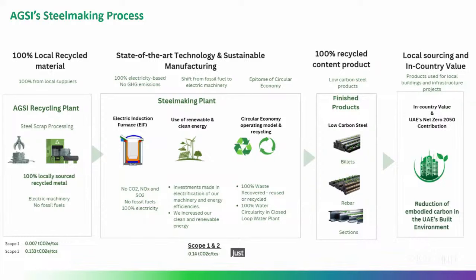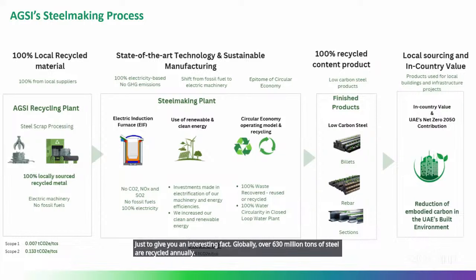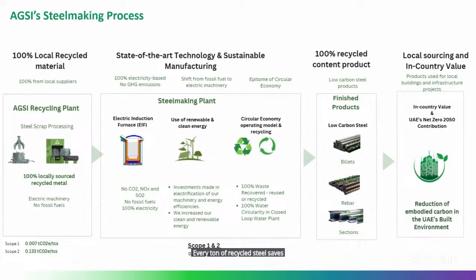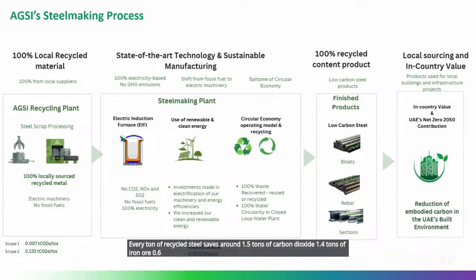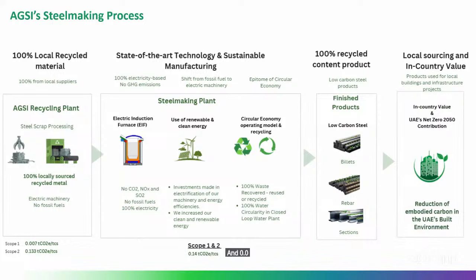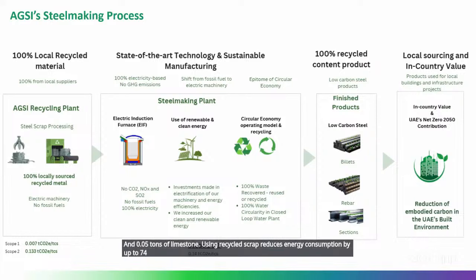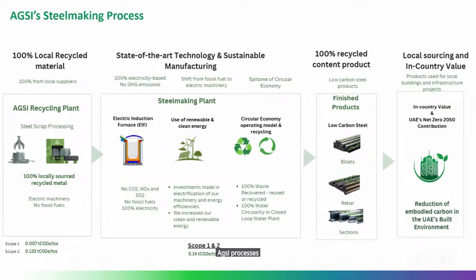Just to give you an interesting fact, globally, over 630 million tons of steel are recycled annually. Every ton of recycled steel saves around 1.5 tons of carbon dioxide, 1.4 tons of iron ore, 0.6 tons of coal, and 0.05 tons of limestone. Using recycled scrap reduces energy consumption by up to 74% compared to using virgin iron ore. AGSI processes around 40 to 50,000 tons of local scrap per month, enough to build the steel structure of a Burj Khalifa-sized tower every 45 to 50 days.